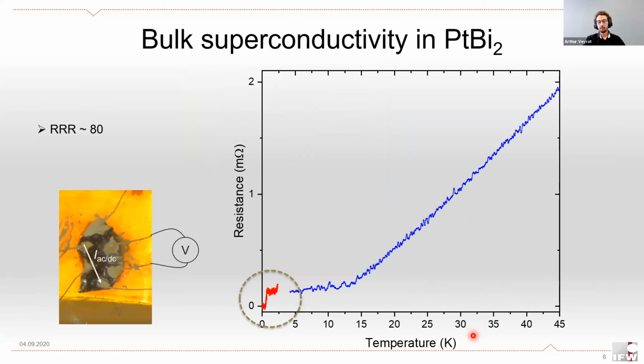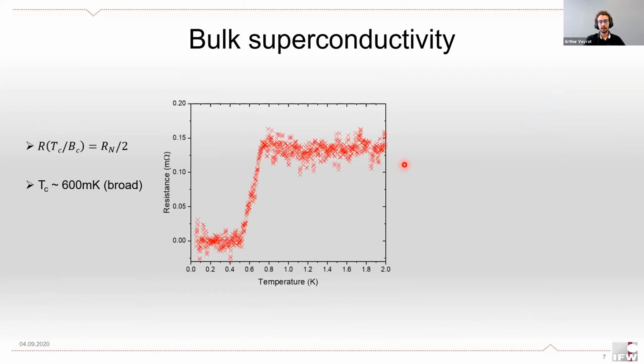Then we cooled down our samples even further using a dilution fridge. And these are the measurements that we got. So we had the nice surprise of finding out trigonal platinum bismuth 2 is actually a superconductor at low temperatures. If I zoom in on this, you can see the superconducting transition happening at around 600 millikelvin. So here I define the critical temperature as being that for which the resistance reaches half of its normal value, and I will use this definition throughout this talk.